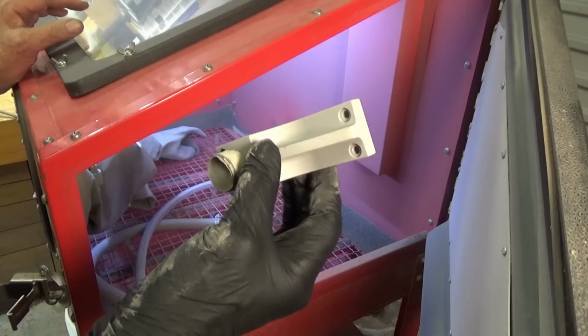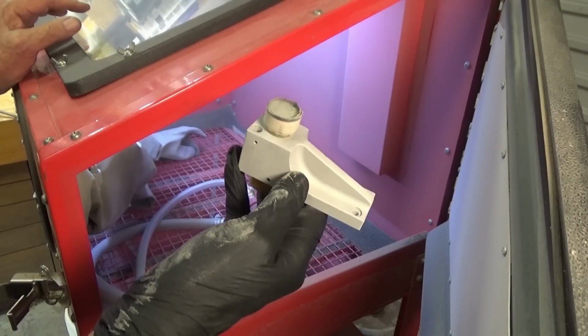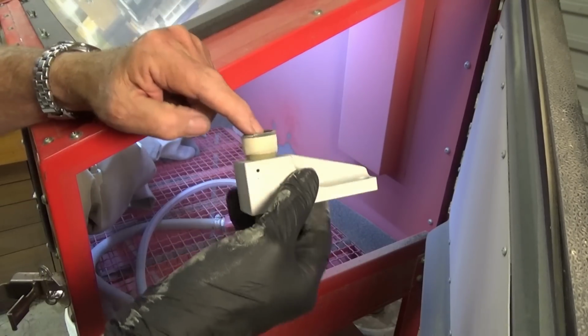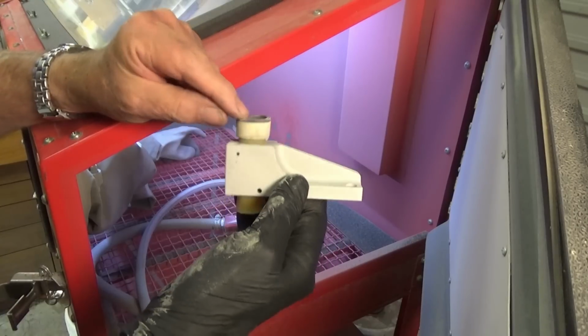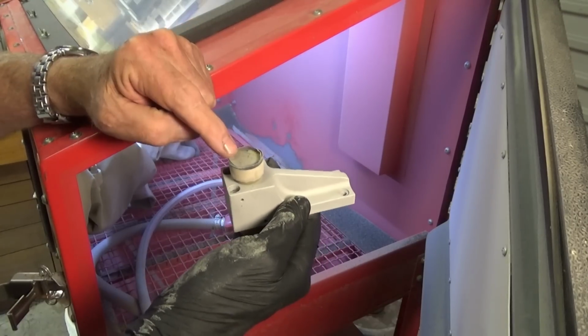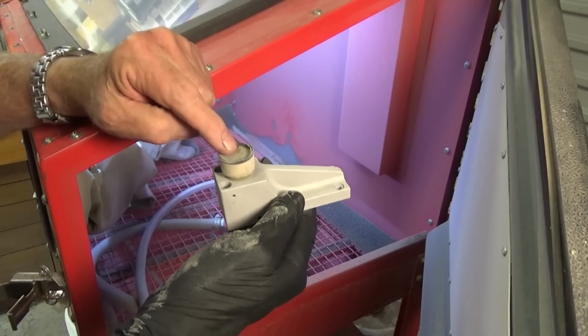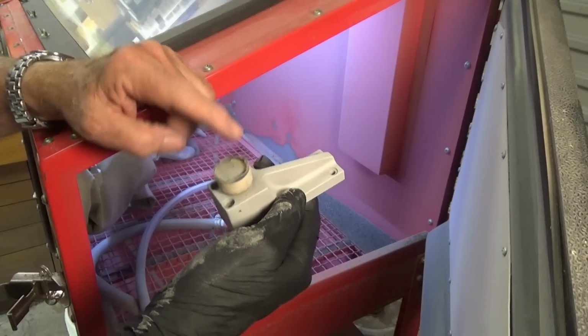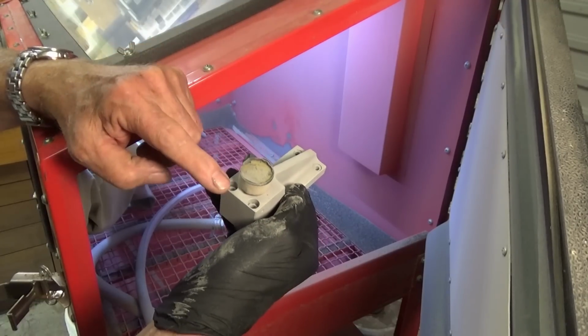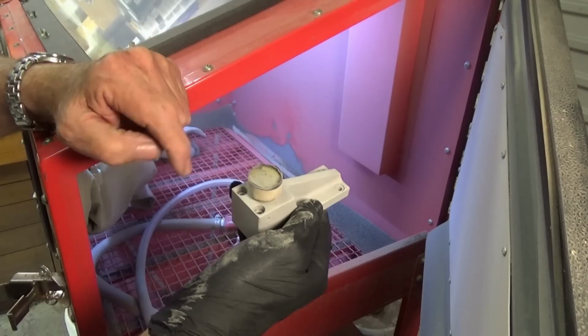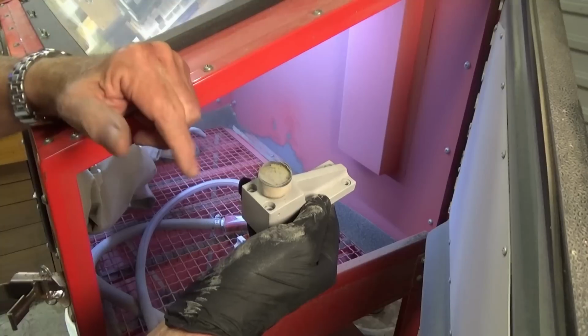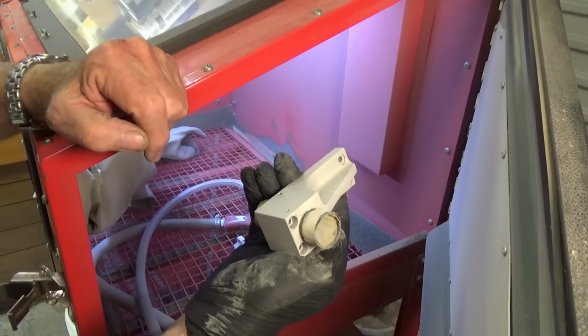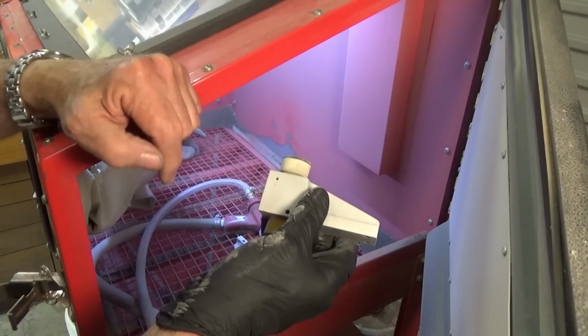So those parts now are nice and clean on the outside, and these silicone rubber plugs here are just to keep the grit out of the bore in the casting. Now try not to touch these. These need to go in the ultrasonic cleaner along with all of the other parts, just to ensure that there's no grease or oil in any of the threaded holes, and then from there we'll do the powder coating on these. But yeah, that sandblasted finish makes the powder coat stick like crazy.